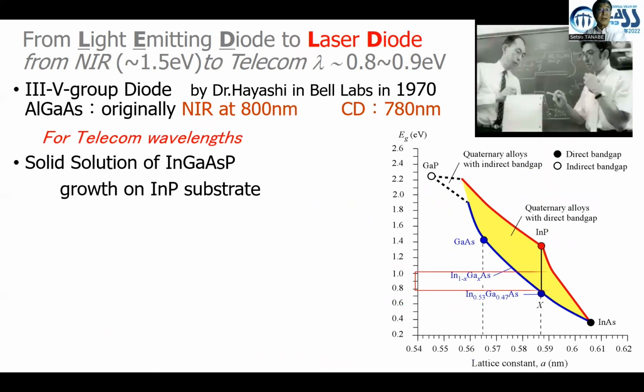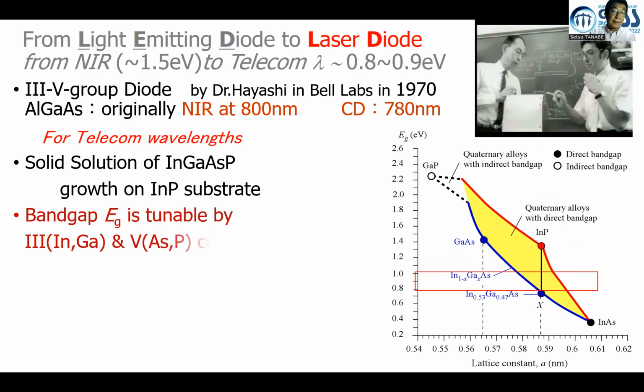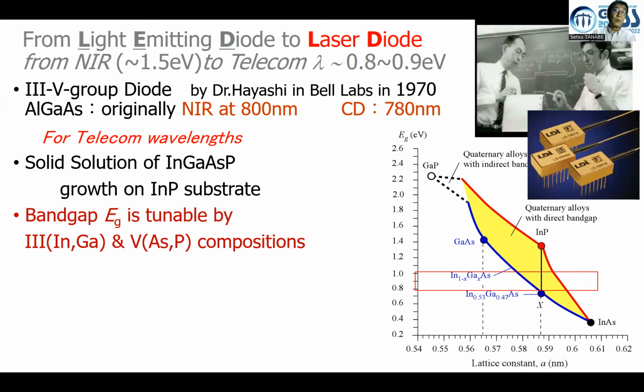At the same time, there was a development of light-emitting diodes and laser diodes. Laser diodes are very important for the information transceiver. Depending on the 3-5 group semiconductor, an indium phosphide single crystal can be used as a substrate for growth by chemical vapor deposition of the mixed alloy solid solution, which is a compound of indium gallium, group 3, and arsenide phosphide, group 5, a 3-5 group semiconductor, and the band gap can be